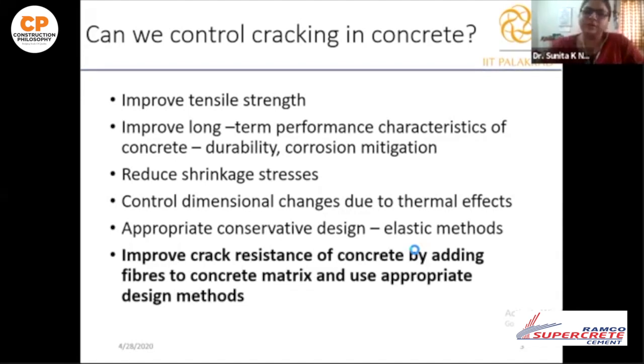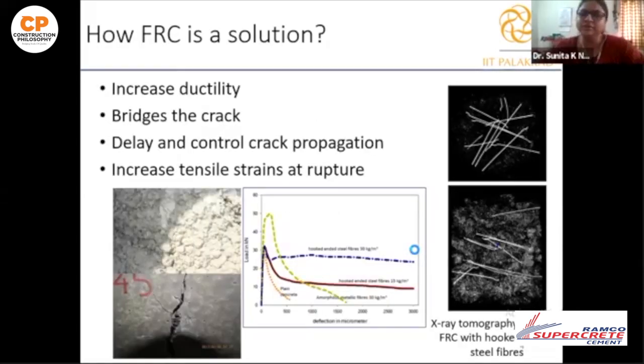And for this, one option, this is not the exhaustive option, one option is to add fibers to the concrete matrix. Because what fibers do is improve the crack performance. Essentially, the fibers would bridge the crack. It does not mean that the cracks will not happen, but it means that even if it occurs, the cracking would be very limited in its crack widths, because the fibers would increase ductility, delay and control crack propagation and increase the tensile strains at rupture.